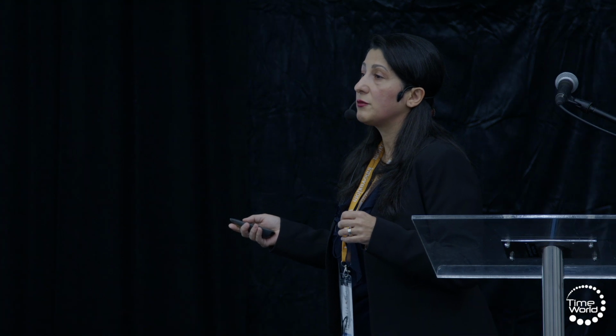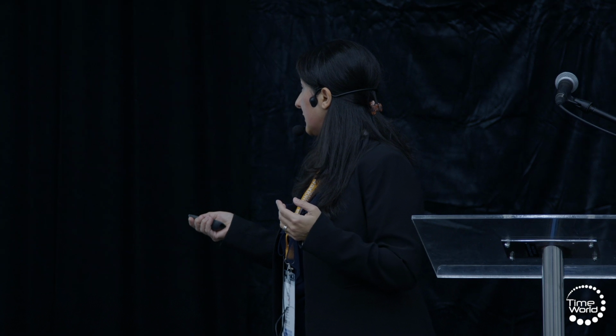So it means that one of the other ways that we can reduce the amount of platinum or precious metal, or even iridium, inside the catalyst layer is changing the support, having proper support in order not to go through the corrosion. Second is shaping this iridium or platinum particle, or making alloy, in order to reduce the amount of the platinum or iridium that we have inside the stack.